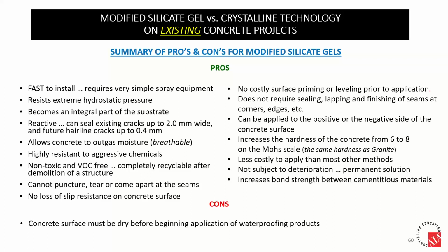So pros and cons, really the only con to use the silicate gel is that the surface must be clean and dry for application. Where with the crystalline slurry, a wet surface is acceptable. But the pros: fast, easy, very simple equipment, extreme hydrostatic pressure resistance, becomes integral, remains reactive, will heal a 2 millimeter crack on install, and in future will heal a 0.4 millimeter crack as it begins to form. It allows outgassing. And what that means is, let's say we're waterproofing a parking structure, and we know it has received water in the past that's going to rust the rebar. If we apply a silicate gel, no more water can get in, but the water that's trapped can evaporate. So over time, that rebar will become completely dry.